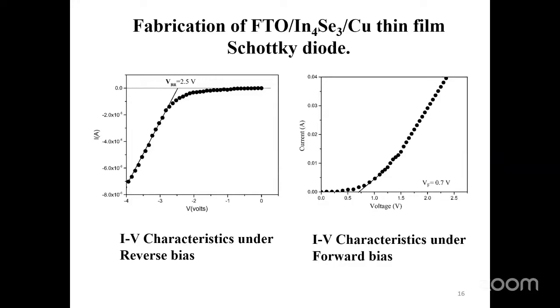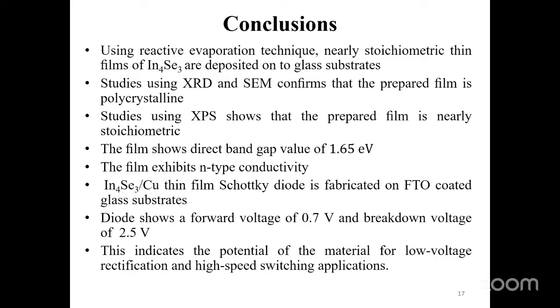So this is our conclusion. Using the reactive evaporation technique, nearly stoichiometric In4Se3 films are deposited on glass substrate. XRD and SEM confirm that the samples are polycrystalline. XPS analysis shows that the prepared sample is nearly stoichiometric. The sample shows a band gap value of 1.65. The film is N-type. A Schottky diode is fabricated on FTO coated glass substrate. The diode shows a forward voltage of 0.7 volt and a breakdown voltage of 2.5 volt. And our study shows the potential of this material for low voltage rectification and high speed switching application.